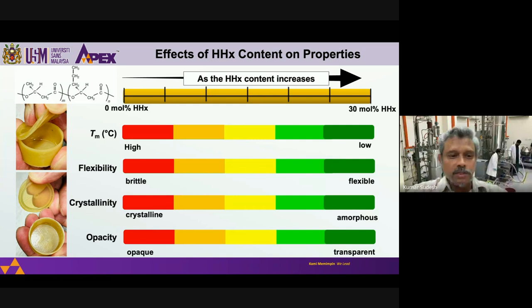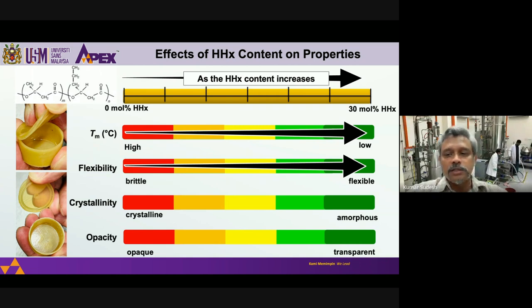For example, the melting temperature of the material. By increasing the HHX molar fraction, we can decrease the melting temperature. So this polymer can be melted at a lower temperature. And by increasing the HHX molar fraction, we can also control the flexibility of the polymer. In other words, higher HHX gives you a polymer that is more flexible. The crystallinity is also an important feature of materials. The more crystalline a material is, the harder it becomes. The opposite of crystalline is amorphous, so making it more amorphous makes it more flexible also.